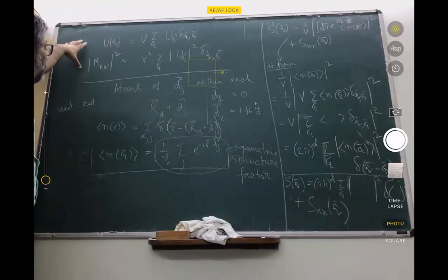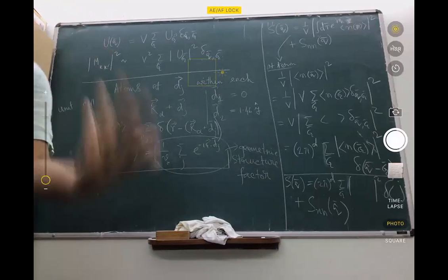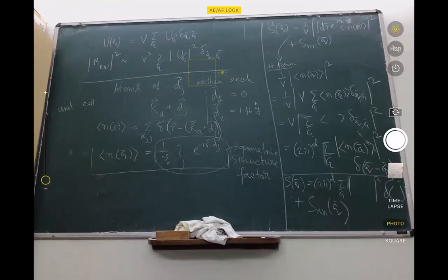And then when you come to this, what is assumed here, and in the whole analysis that we did earlier, is that the potential U that the scattered particles experience is the same at all lattice points. Now, if it so happens that there are different types of atoms in each unit cell, there's no reason to assume that the scattering potential they provide to the incoming particles would be the same. So it can vary with what type of atom is sitting where.